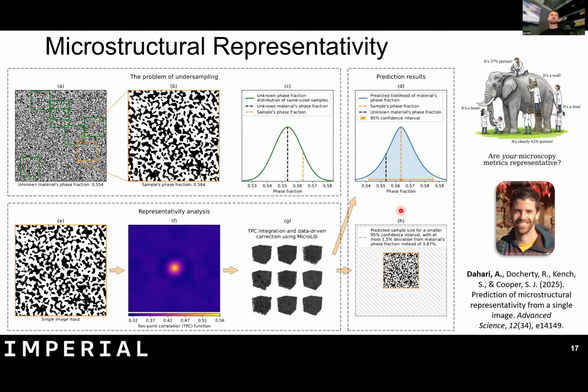And we have published a method that you can get from ImageRep, where you can pass in a single image and, using 2-point correlation statistics extracted from a fast Fourier transform, you can work out your confidence interval. So you can put in a single segmented image and say, this image is 37% porous, with 95% confidence of being within X% of the true value of the bulk material. So it's a really useful way of getting a sense.